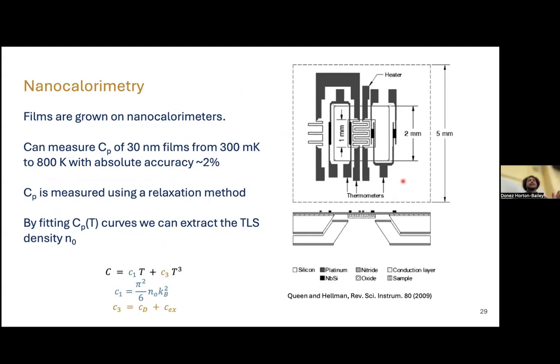These materials are studied in 2 different ways. So I mentioned calorimetry. Previous members of our group developed these calorimeters on a chip, these small half a centimeter nanocalorimeter devices. And so you can deposit your film onto the center of this device, and with this complex set of thermometers and heaters, you're able to figure out the heat capacity of your film as a function of temperature. So at various temperatures, if you cool down your system, the heat capacity is going to be different. And based on the shape of that curve, we can get an idea of the density of TLS in the film.